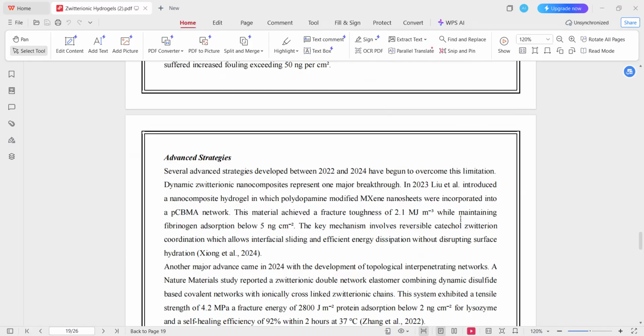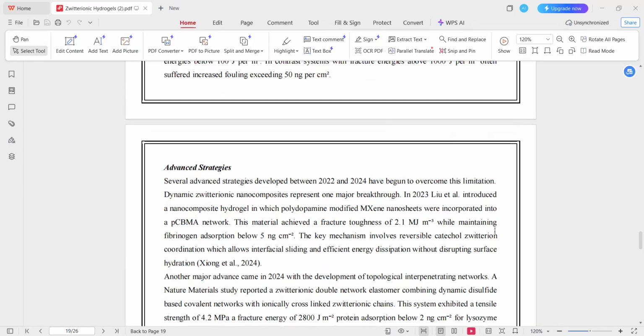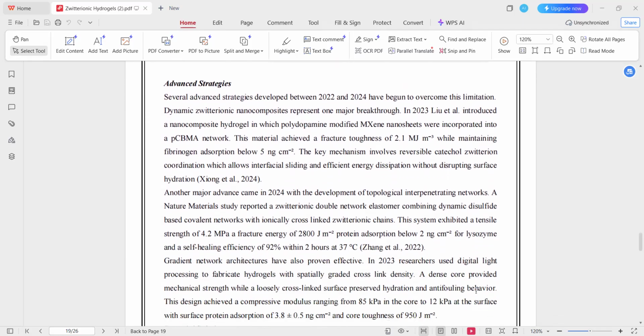Another major advance came in 2024 with the development of topological interpenetrating networks. A Nature Materials study reported a zwitterionic double network elastomer combining dynamic disulfide covalent bonds and ionically cross-linked zwitterionic chains. This system achieved a tensile strength of 4.2 megapascals, a fracture energy of 2800 joules per square meter, protein adsorption below 2 nanograms per square centimeter, and a self-healing efficiency of 92% within 2 hours at body temperature.